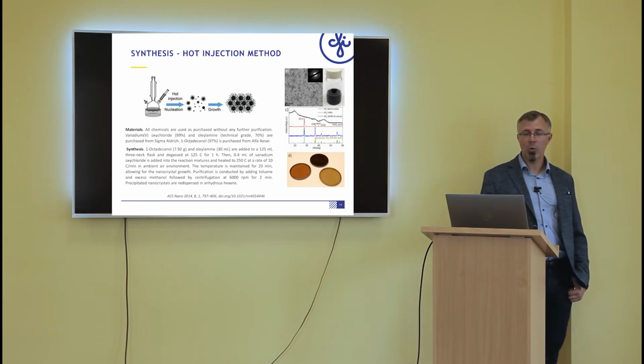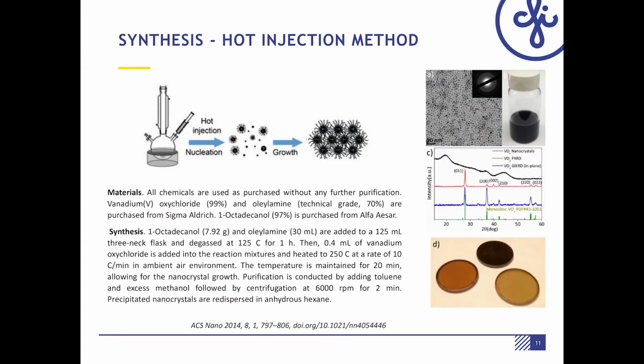The next method, the hot injection method, allows us to produce very fine vanadium dioxide nanoparticles. But after synthesis, these nanoparticles have a crystalline structure which has no thermochromic properties. To modify the crystalline structure of nanoparticles, thermal sintering can be used. These tiny nanoparticles are very good for producing vanadium dioxide based inks for inkjet printing.